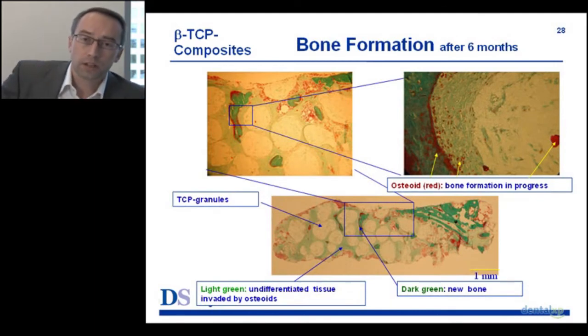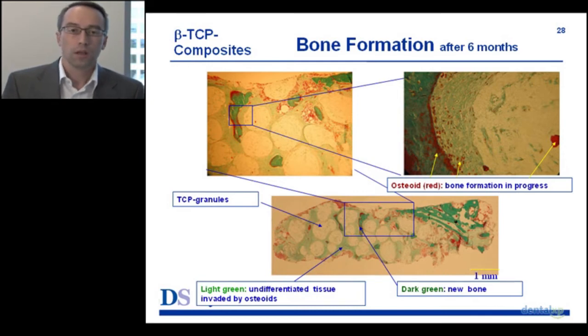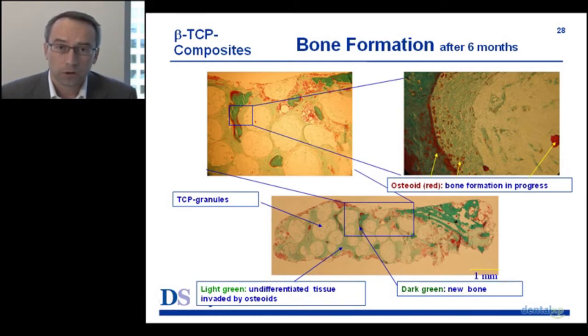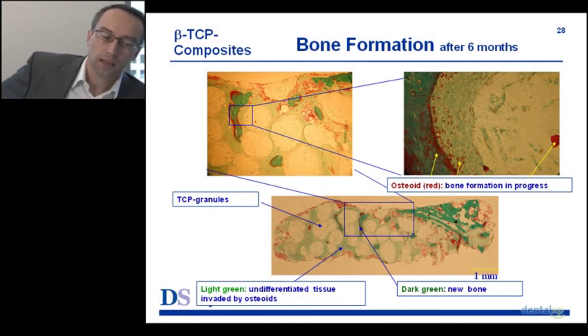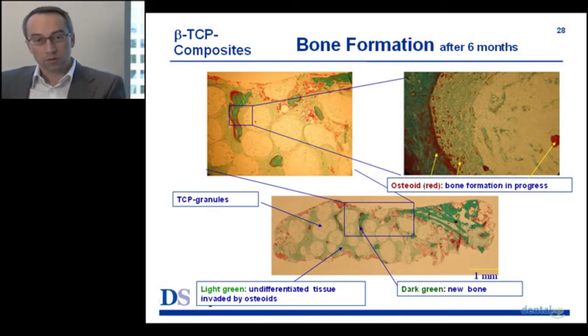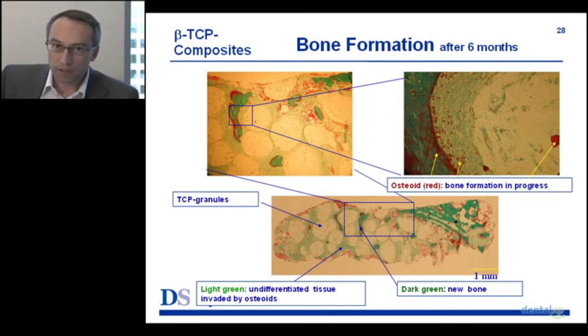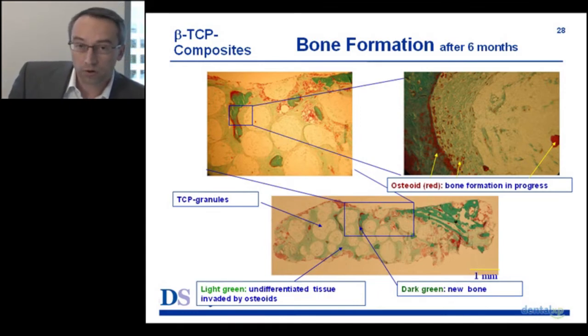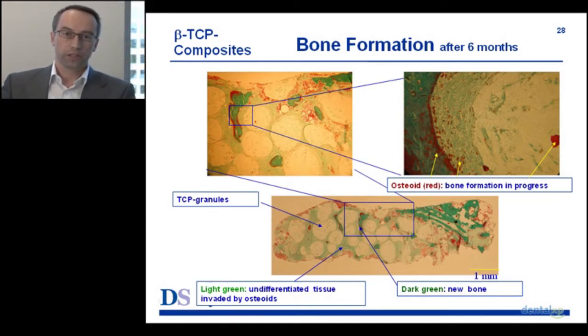The summary of this clinical study we conducted in 2003-2004 was as follows. Dr. Schuck, the leader of the study, said that this product or this therapy is safe and preserves the alveolar bone structures in dimension in the short and mid-range term. He found that the predictability of the result was good and that in all patients where he implanted the titanium implant, immediate primary stability was good. In no cases was additional bone augmentation material needed, and wound healing occurred without symptoms. So we have actually developed a working new therapy to help to prevent alveolar ridge resorption.